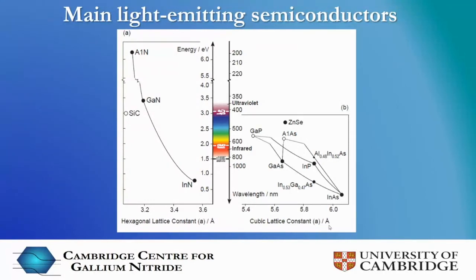If you look at the left-hand side of the diagram, you'll see gallium nitride, which emits in the near ultraviolet, and indium nitride below, which emits in the infrared. And you can mix these two compounds and have indium gallium nitride, a compound with 3 atoms. And it's a bit like cookery. If you have about 10% indium, you get blue light out. If you have 25% indium, you get green light out. So just by varying this composition, you can get light emitted of any color.